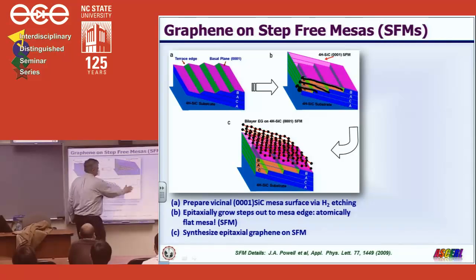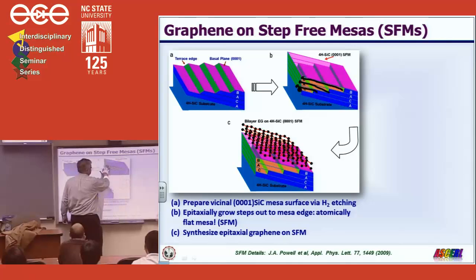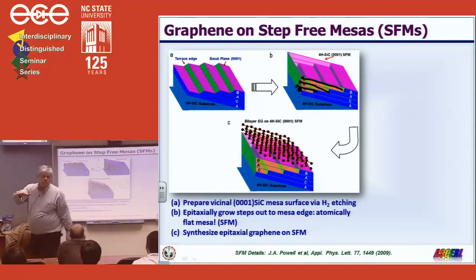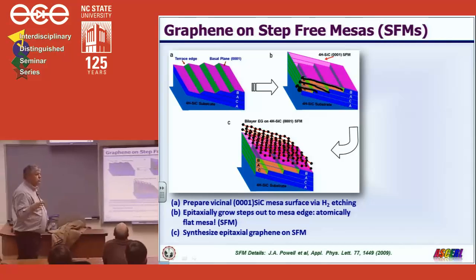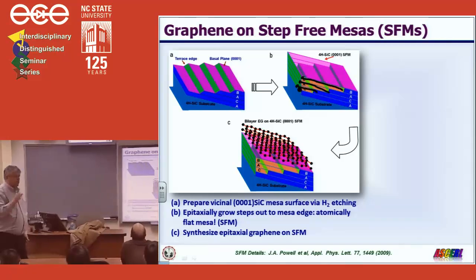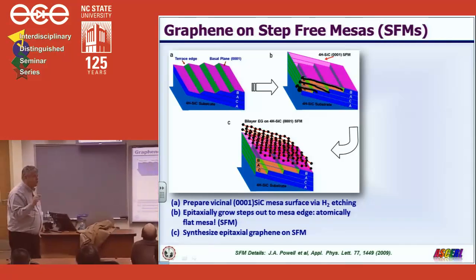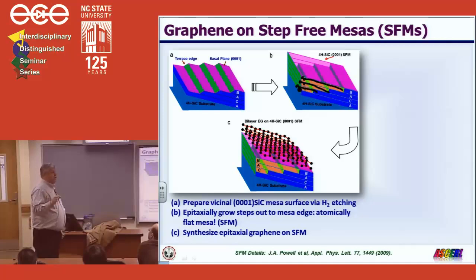And what will happen is, after all the steps are grown out, what you're left with is a mesa that's flat. And there's no more steps, there's no more imperfections on it. This only happens if there's no screw dislocation. So if the mesa has a screw dislocation, it's an infinite source of steps.